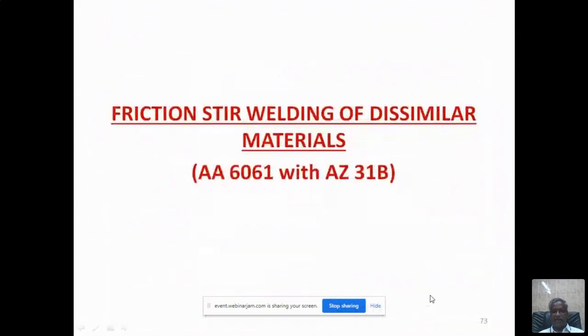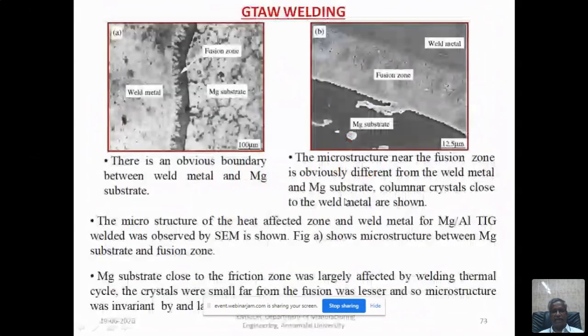And one case study I want to show is for dissimilar joining, because the topic is dissimilar non-ferrous alloys. We joined 6061 with AZ31B, and as I told you, it's very, very difficult by fusion welding. In TIG welding, a lot of intermetallic compounds form at the interface. So immediately after welding, you can break the joint by hand just by bending it, because of the intermetallic formation.